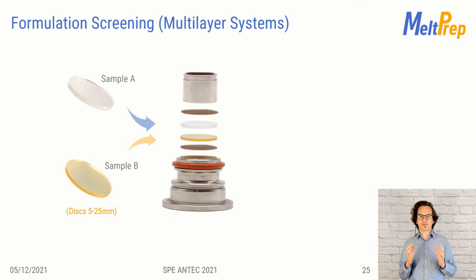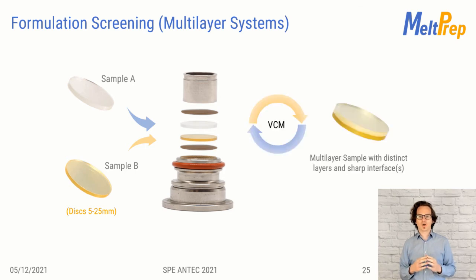VCM allows you to fuse multiple layers to one specimen. So you can prepare various layers in advance, one by one, and load them into the VCM chamber, process them in another cycle into one single specimen. You obtain a multi-layer sample with distinct layers and sharp interfaces.